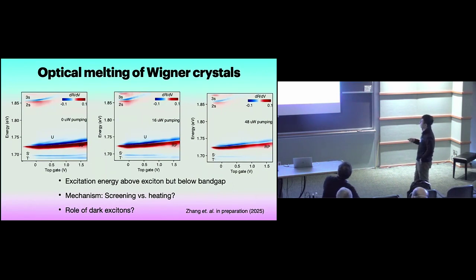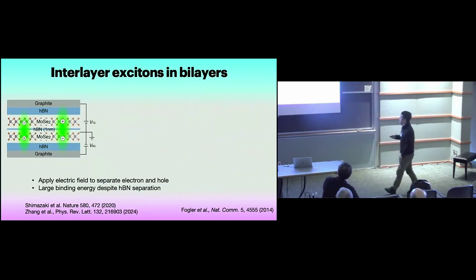So very interestingly, this tungsten diselenide is quite different from MoSe2. They are known to have dark excitons, so you can create a high density of excitons without a lot of pumping power. So one experiment that we are trying to do is to compare these results with what's going on with moly diselenide, because in there you would have much lower exciton density, and then you can see whether the exciton population is really playing a role over here. Okay. So this is in the monolayer case.